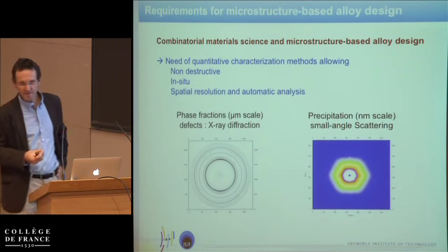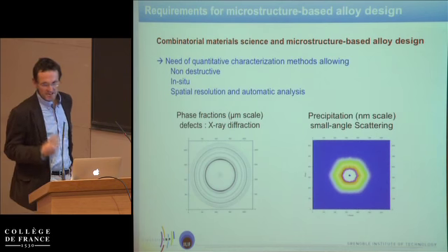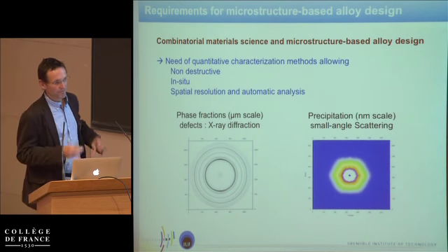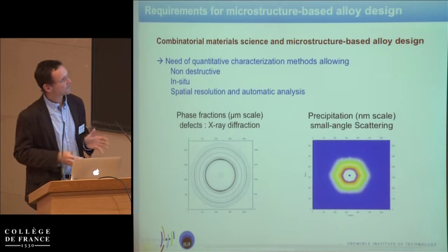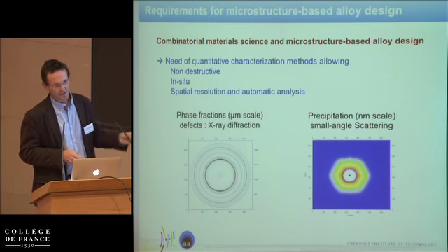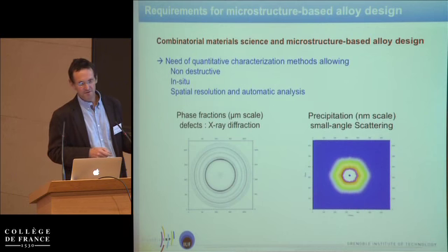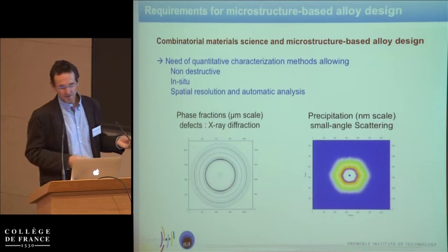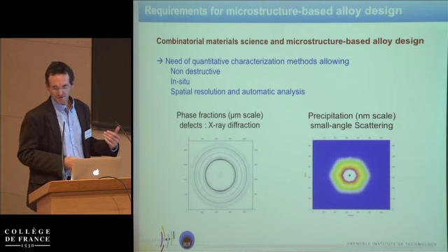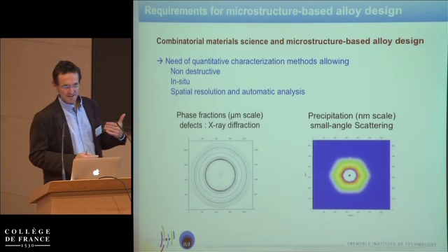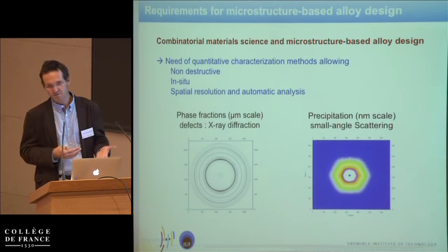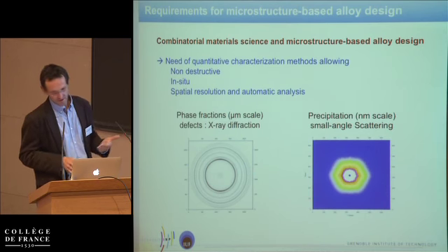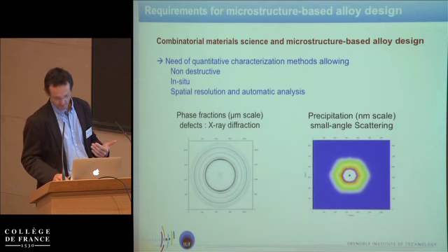And probably the X-ray methods are particularly well suited to that, because the size of the beam is of the micrometer to millimeter size scale, but the size of objects you're probing with these kind of methods are nanometer size. So it's particularly suited to study the microstructure at the nanometer scale, varying in space at the micrometer to millimeter scale. And it's non-destructive and possible for in situ.